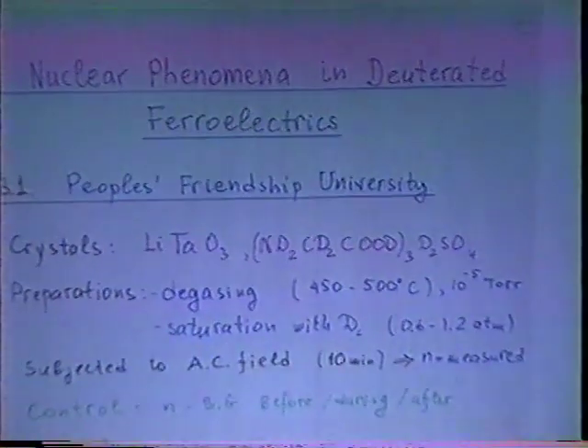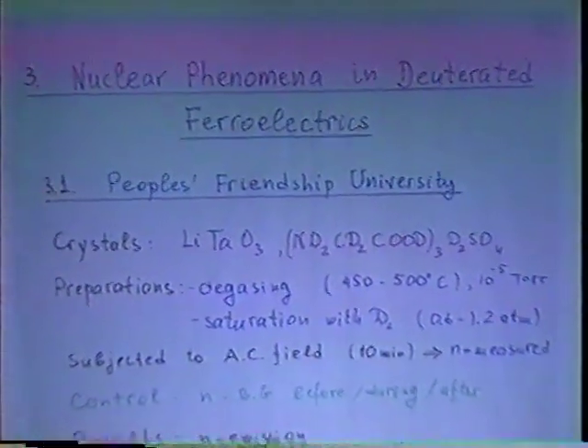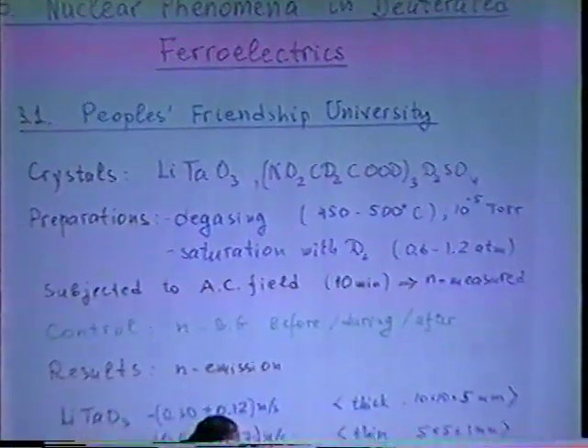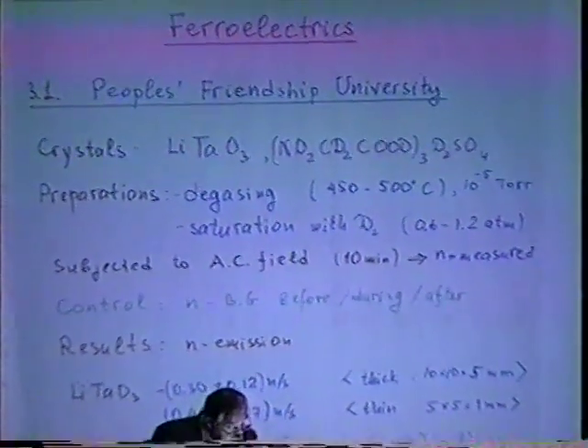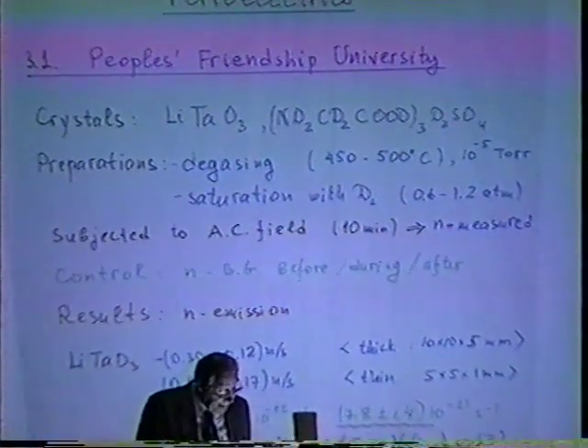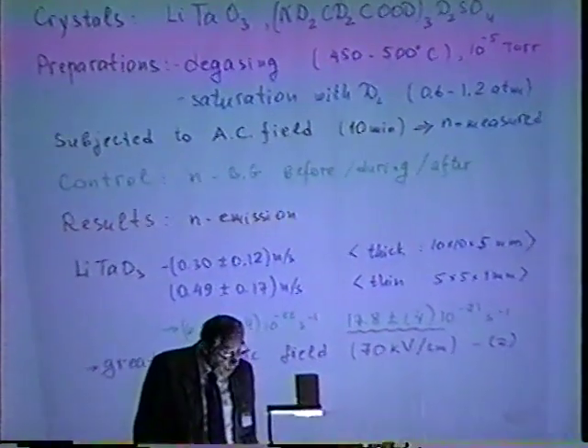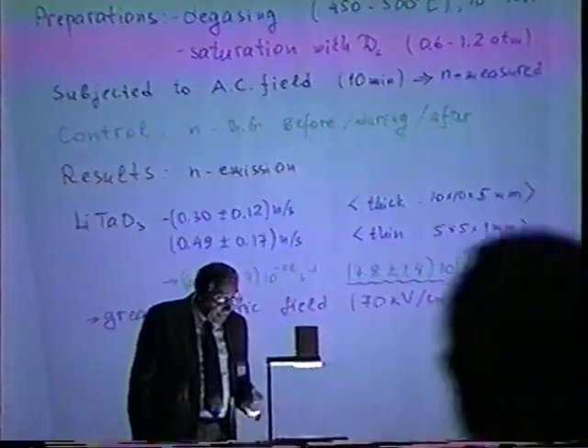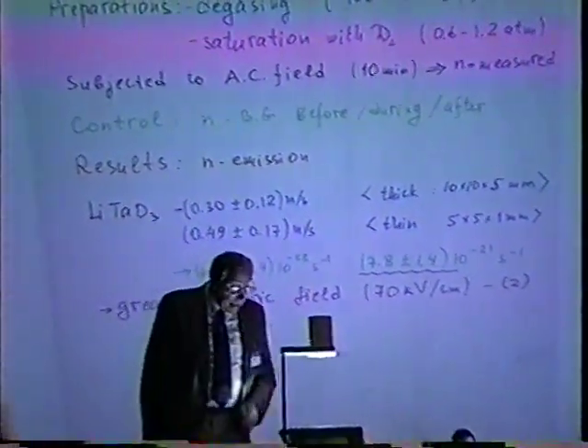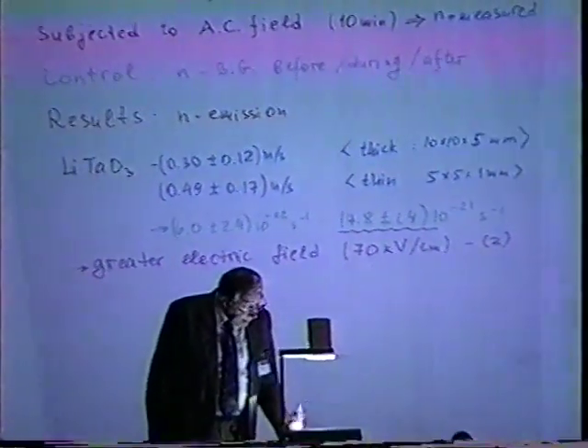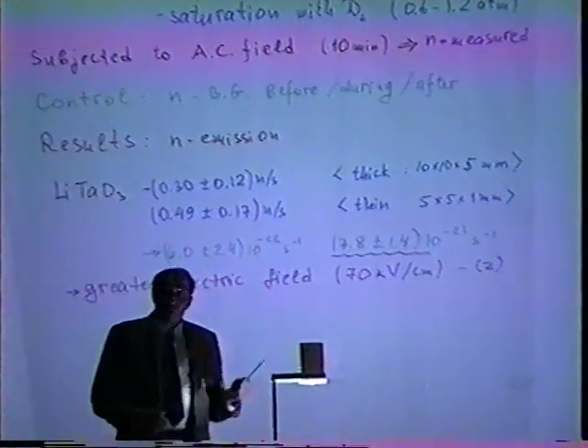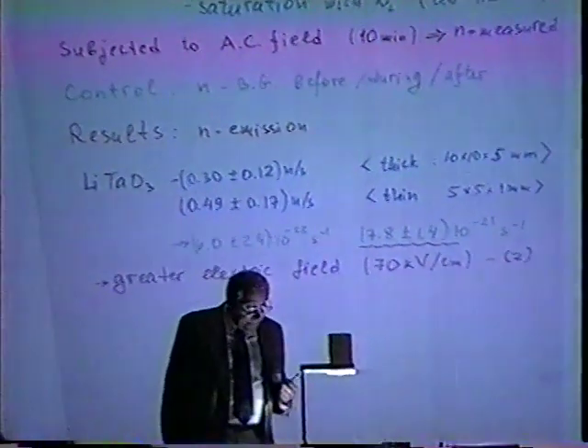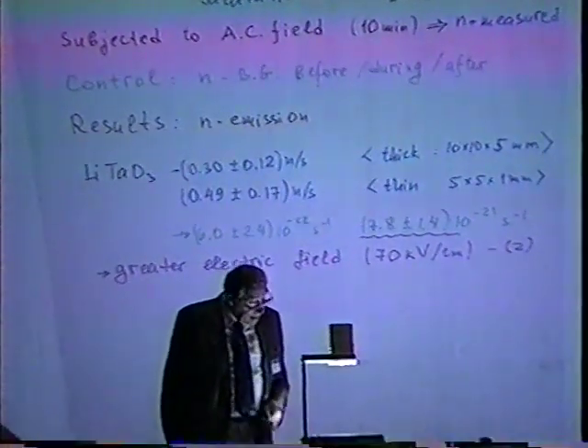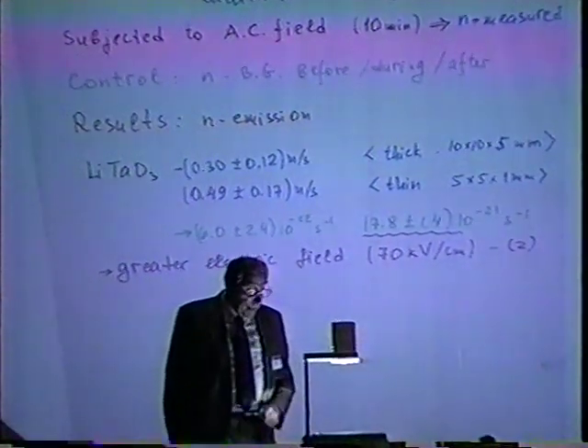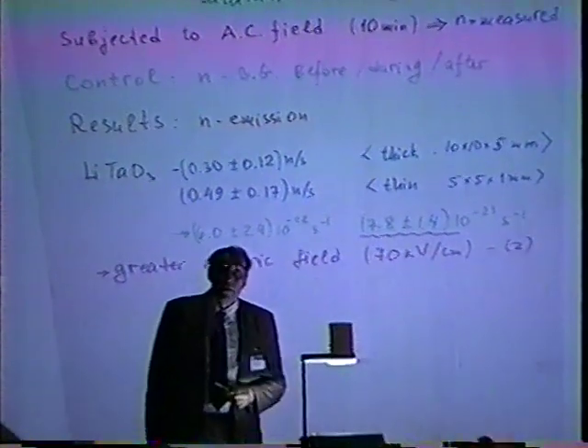The other problem is nuclear phenomena in deuterated ferroelectrics. Two experimental groups are now working in this field. First is the People's Friendship University group, and they studied various kinds of ferroelectrics, deuterated ferroelectrics, and they used an alternating current field applied to these ferroelectrics. Their results are the following. They observed neutron emission during this process of inverse polarization, or reverse polarization. It's not very high, about 1.5 or 2 times the background. The absolute values are shown here.